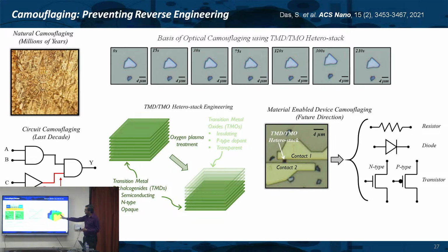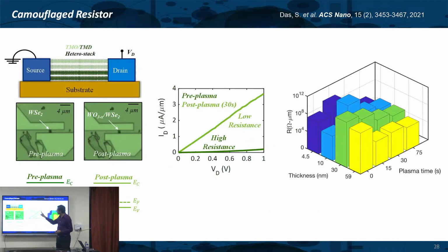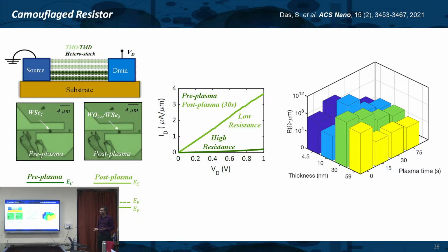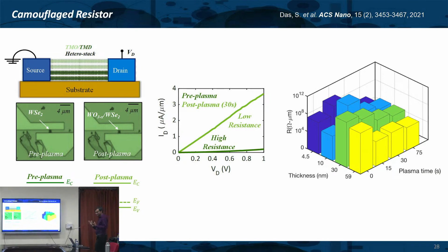Okay, there is some more data, just showing what happens. You see pre-plasma, post-plasma, I can use it as a resistance, because generally you cannot change the resistance value of a resistor, right? But now through oxygen plasma, you see, I can get two resistance values without changing its appearance. So your adversary will not know whether it is a high value resistor or a low value resistor, correct?